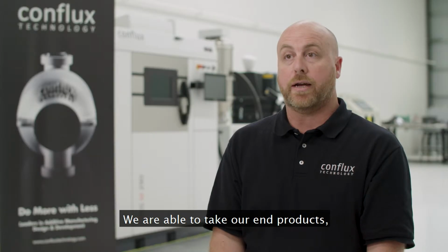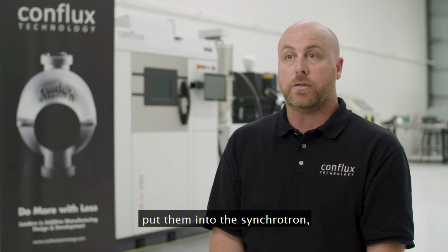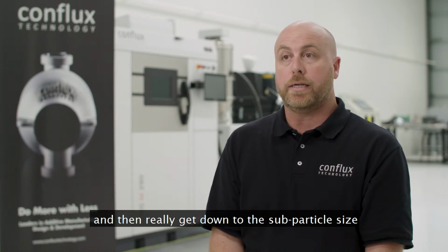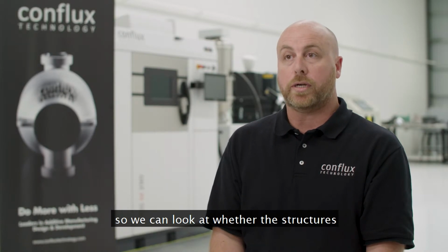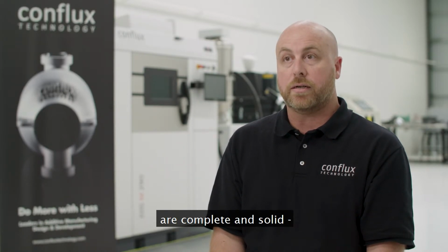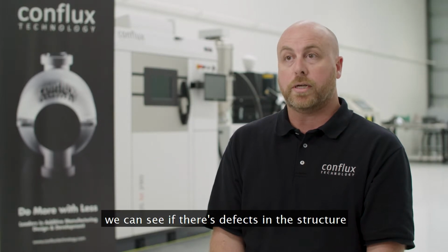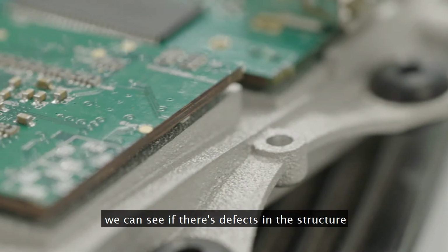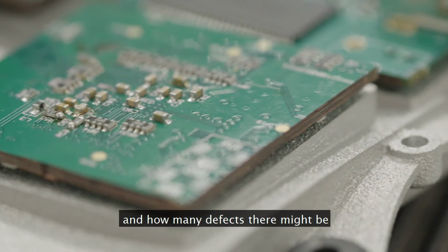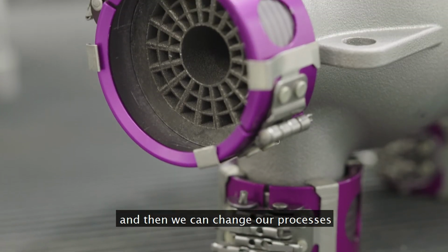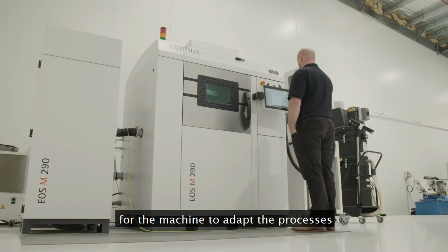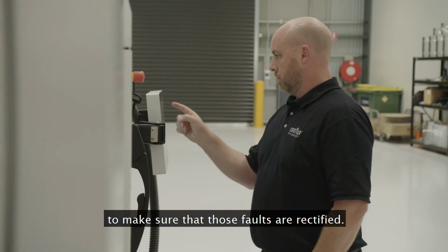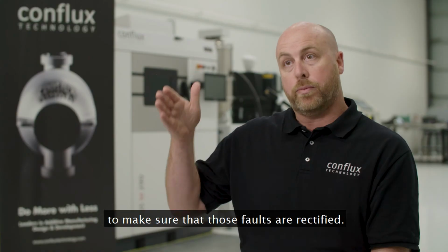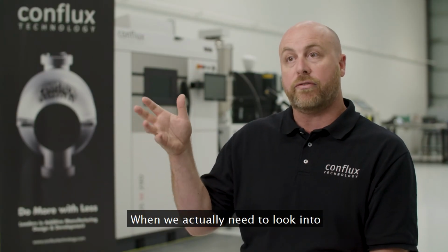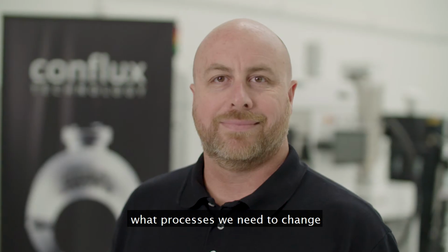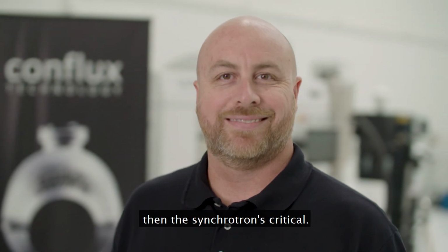We are able to take our end products, put them into the synchrotron, and then really get down to the subparticle size, so we can look at whether the structures are complete and solid. We can see if there are defects in the structure and how many defects there might be, and then we can change our processes for the machine to adapt the processes to make sure that those faults are rectified. When we actually need to look into the fundamental reasons why and what processes we need to change, then the synchrotron is critical.